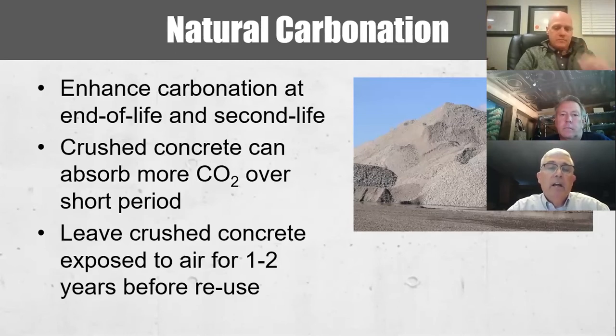And typically, concrete is not thrown away. Its weight, its volume really moves it more towards continual recycling. And so you see it crushed and oftentimes used as roadbed or as backfill. It can even be used as aggregate for new concrete. Ideally, studies have shown if you can leave the crushed concrete exposed to air for a period of 1 to 2 years before reuse, you're really enhancing and maximizing this process.